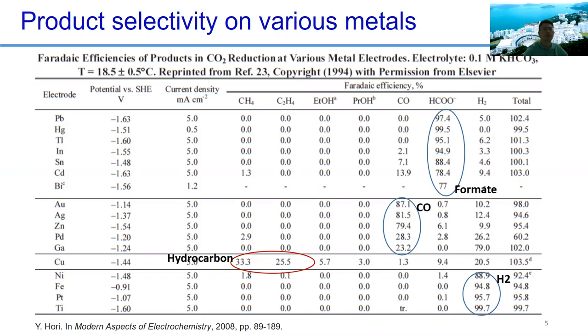Okay, so the first category is where the main product is formate or formic acid, including lead and mercury. So we can see that the majority of the product is formic acid. For gold, silver, zinc, palladium, the main product is carbon monoxide. Okay. And for platinum, nickel, iron, the main product is actually hydrogen. So that means the hydrogen evolution is much easier on this surface, instead of carbon dioxide reduction.